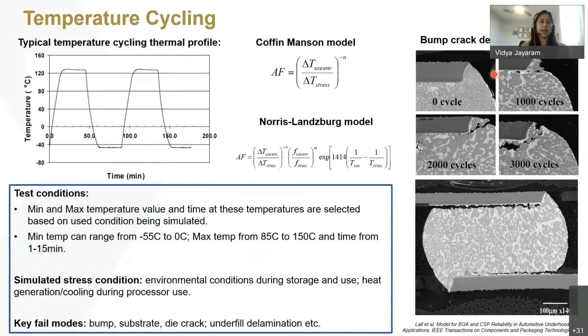The first one being temperature cycling. This is one of the most common types of reliability tests that we would use to accelerate different fatigue related failure modes. What it is, is cycling from a really low temperature to a really high temperature and going in cycles with a specified period of time between the high and low temperature cycles. So depending on the use conditions, these three parameters can be varied to simulate the environmental condition that you would expect to see as part of the product use case.